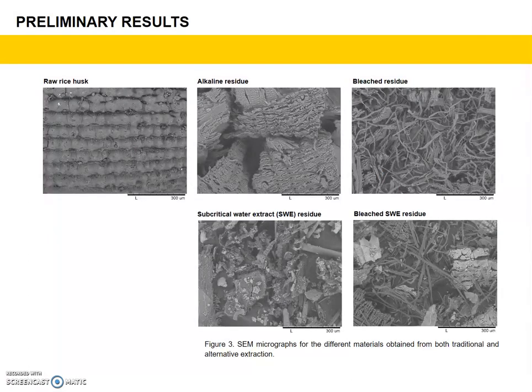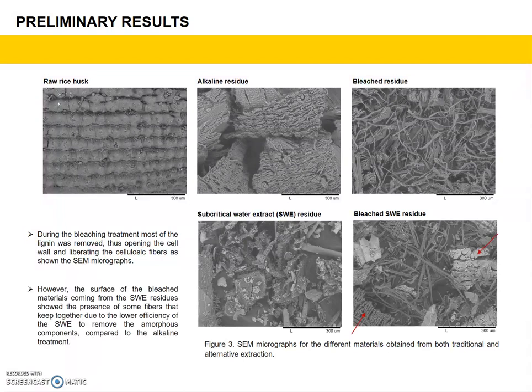During the alkaline and bleaching treatments, the amorphous component and most of the lignin were removed, thus opening the cell wall and liberating the cellulosic fibers, as shown in the SEM micrographs. However, the surface of the bleached materials coming from the subcritical water residues shows the presence of some fibers that keep together due to the lower efficiency of the subcritical water extraction to remove the amorphous component compared to the alkali treatment.